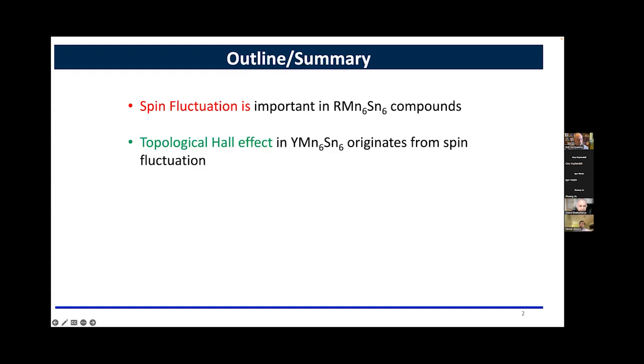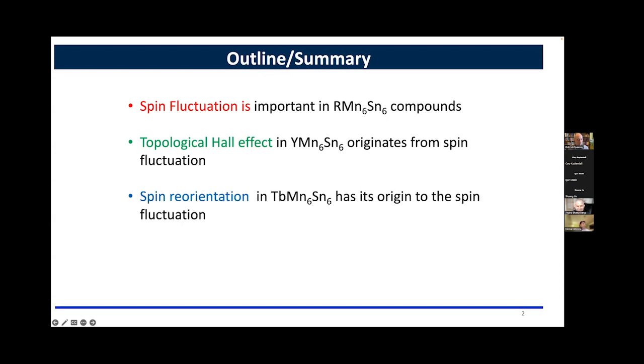The first thing that we'll talk about is the topological Hall effect in yttrium manganese 166. The topological Hall effect, what we have found, originates from spin fluctuation or thermal fluctuation causing the spins to fluctuate. And in terbium manganese 166, which has an interesting spin reorientation transition, these fluctuations also play a role in driving that spin reorientation.